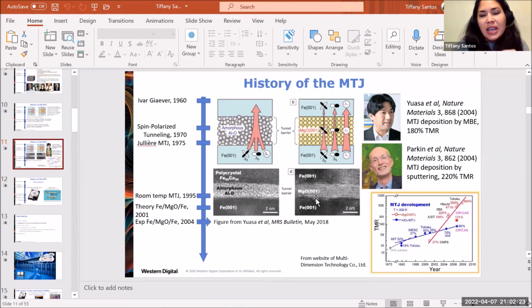Now, in the case of the MgO tunnel barrier, this is a specific case. It's a very nice study led first by a theoretical prediction and then later shown experimentally. It's referred to as a spin filter, where you have this unique combination of MgO and an iron-based electrode that gives you tunneling of fully spin polarized electrons from the iron.